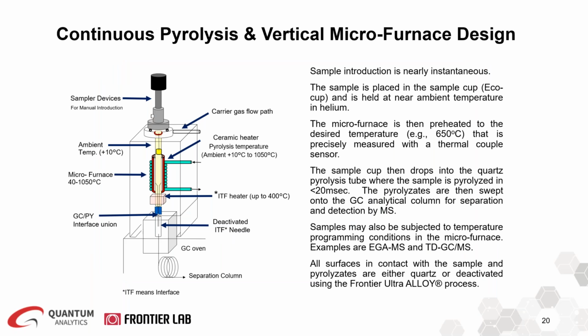Lastly, let's talk about what sets the vertical microfurnace design apart from others. Sample introduction is nearly instantaneous. The sample is placed in the sample cup and is held at near ambient temperature in helium. The microfurnace is then preheated to the desired temperature that is precisely measured with a thermocouple sensor. The sample cup then drops into the quartz pyrolysis tube, where the sample is pyrolyzed in less than 20 milliseconds. The pyrolytes are then swept onto the GC column for separation and detection by MS.